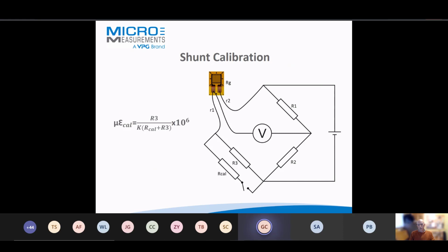So with this circuit, we can calibrate it, and one of the ways to calibrate it is to use a thing called shunt calibration. Again, any of you who've done electronics will know, of course, the simple calculation for resistors in parallel. And there's a complete calculation here to convert that change of resistance into microstrain. And let's say I choose our cal to equal 1000 microstrain. So I will close the switch, resistance change will be equivalent of 1000 microstrain. Now this particular 3-wire circuit, R1 would cause this value to be slightly lower than you would expect.